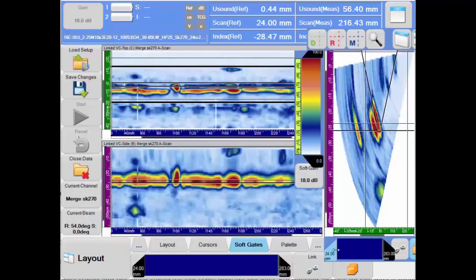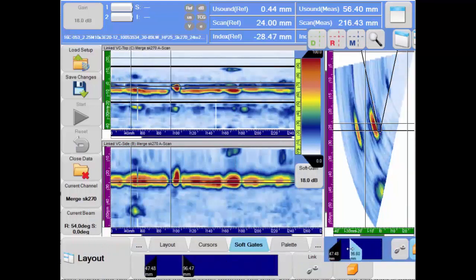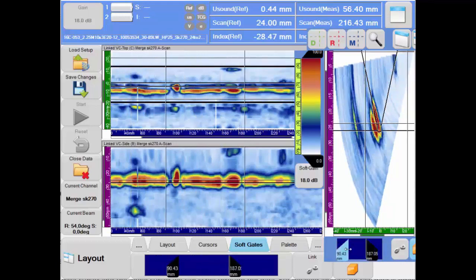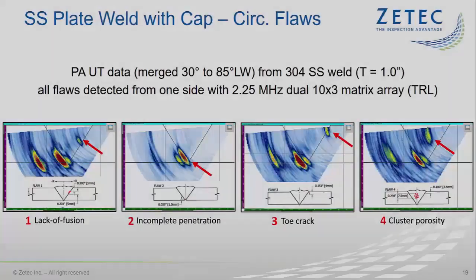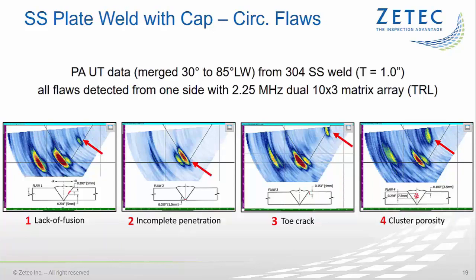Still using the projection gates, the analyst can easily isolate and visualize every individual indication at different locations along the weld. On this slide, you can see the end view images from the individual flaws, generated with the same merged data group. The lack of fusion defect on the near side of the weld is clearly detected even through non-specular reflections on the upper and lower edge. An incomplete penetration defect, 1.5 mm high, is easily detected and discriminated from the regular root echo.